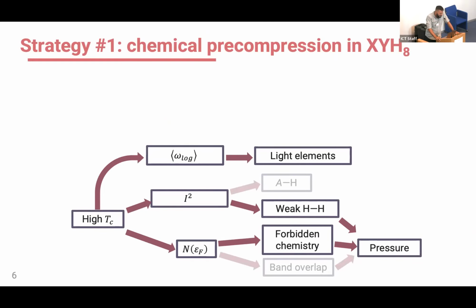And the reason is that we want superconductors that can have a practical consequence in technology and energy that we so desperately need. We deemed it not realistic to have room temperature at the same time, but rather we are much more interested in going to ambient pressure. So the first way that we could go about this is to go through a pathway that has already been tested, which is to, of course, exploit the hydrogen-hydrogen interaction like in lanthanum hydrogen 10. And for that, as I said, we need pressure.